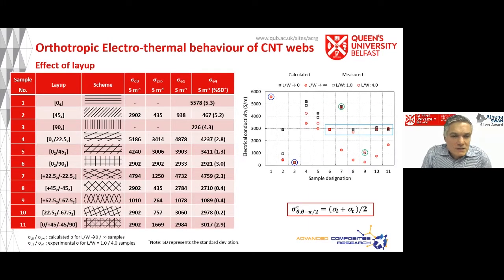Now, this is a busy slide, so I won't spend too much time on it, but I will just explain what I've got here. I've got a lot of carbon nanotube layups here, as you can see, and then I've got the calculated conductivity for a very low aspect ratio and the conductivity for a very high aspect ratio. Where one approach is 0, the other approach is infinity. Of course, experimentally we can't do that, so I've got for comparison an aspect ratio of 1 and an aspect ratio of 4. And what you will see is that when your sample has a significantly biased directional layup, like 1 to 5, then the aspect ratio has a noticeable effect on conductivity.